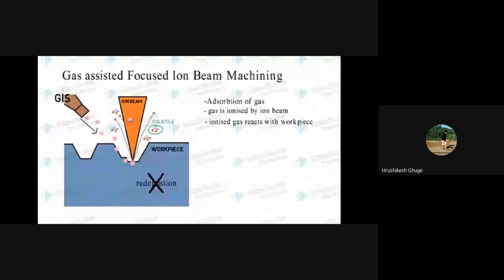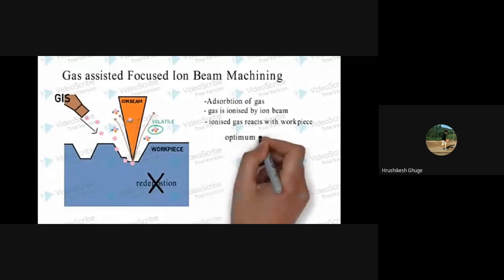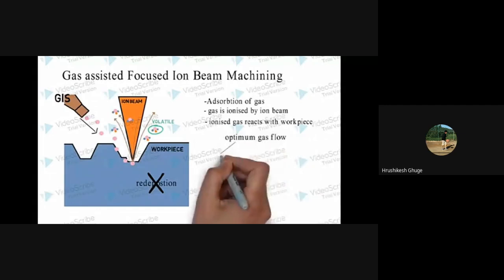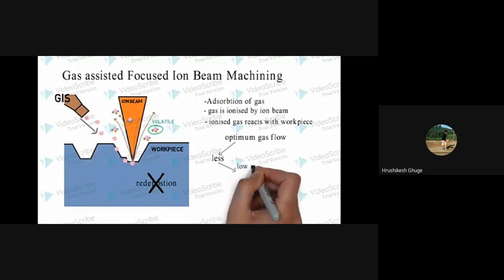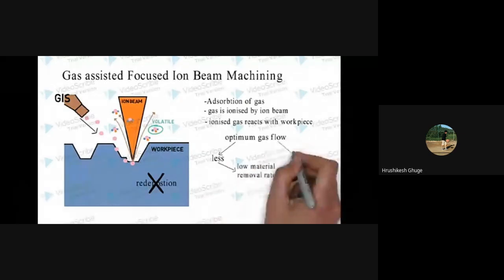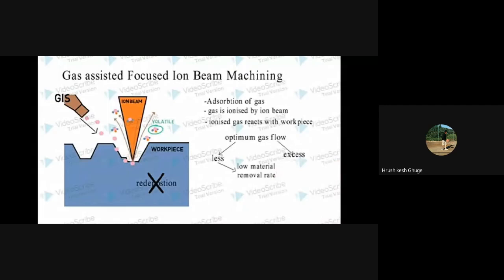So the number of gas molecules, or the amount of gas injected at the milling surface, is kept optimum, because if the gas is lower, that is in less amount, it will generate less material removal, that is low material removal rate. But if there is an excess of gas, the gas atoms will directly interact with the ions and not the workpiece, that is the substrate. So there will be no workpiece atom removal, and again a low sputtering rate. So either a high or low amount of gas results in low material removal rate.